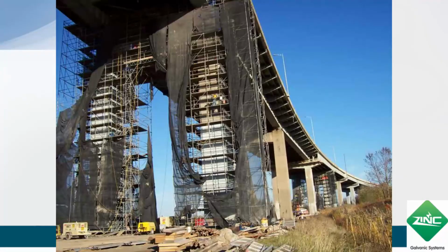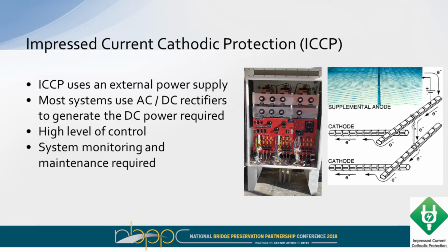In this case, they used a humectant to increase the moisture at the anode for higher current. Impressed current cathodic protection, we saw that earlier. This is just an example of cathodic protection. There's been a lot of discussion about that. Impressed current systems give you a high level of control.